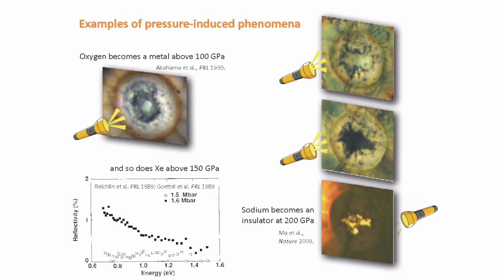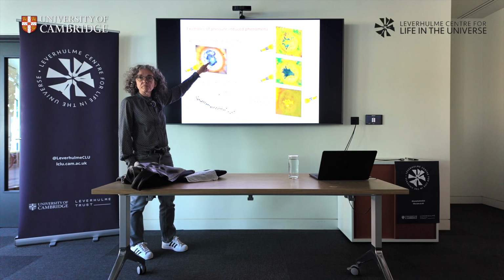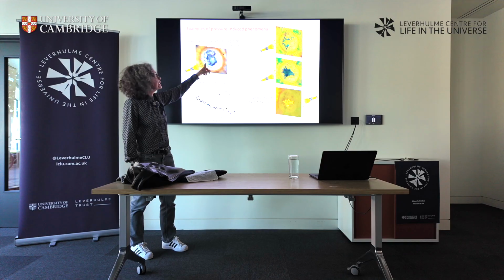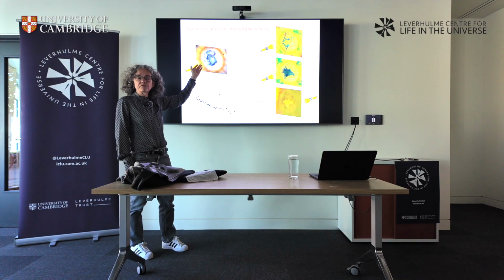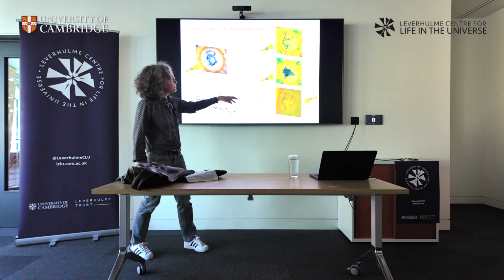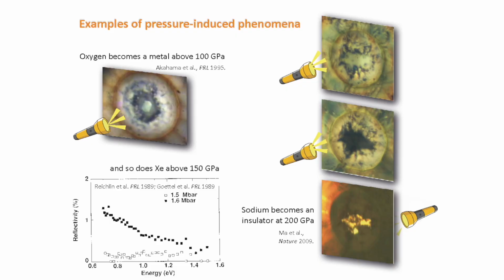So you have the light from the top. If you see light shining from this oxygen crystal, it means that it's a metal. That happens above 100 GPa. Oxygen becomes a metal. The inverse can happen. For instance, well, we don't really care in our sciences for this, but still it was very interesting.